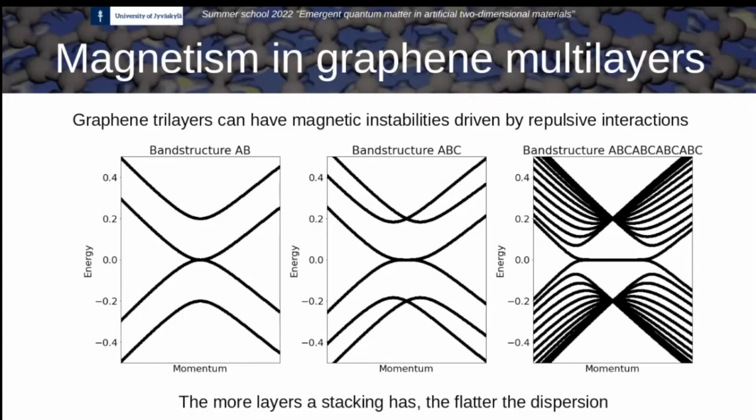And these flat bands are some states that live in the top layer, mainly, and in the bottom layer. And they are also known as drumhead states of nodal line semimetal. So you can think that rhombohedral graphite is a special type of topological state, known as a nodal line semimetal. And these flat band states are the surface states of that topological state.